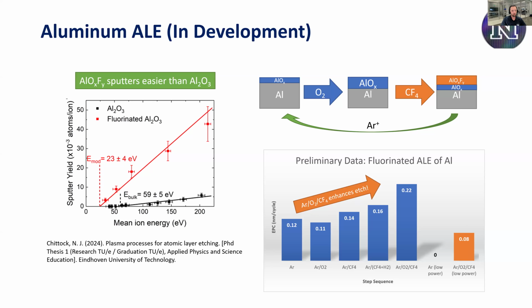Maybe that'll work out. And this was informed by work by Nick Chittock out of TU Eindhoven, who's now at Oxford Instruments. Nick had observed, and I think the George group observed something similar in the past as well, that the sputter yield for fluorinated aluminum oxide is quite a bit higher than the sputter yield for aluminum oxide. This was kind of interesting. And we did go ahead over the last few weeks and get some preliminary data on this. And we found indeed that, if you look, we're just talking about the step sequence for right now.